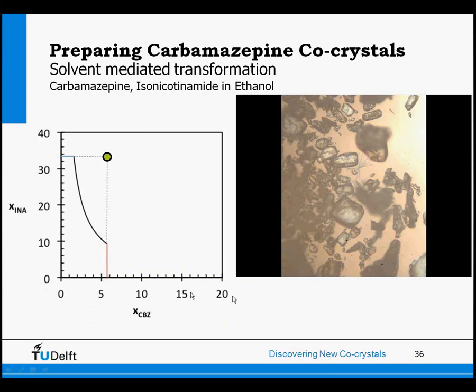Okay. So one thing you can do if you know the phase diagram is to prepare a composition in this point. So you add pure crystals of carbamazepine to a microscopic vial in such a way that you get this concentration in the end if you also add the solvent. You can also add Isonicotinamide crystals, and then you get this composition. And the moment you add ethanol, the crystals will start to dissolve and concentration increases, and you will enter the co-crystal region, and you get supersaturation towards the co-crystal, while you get undersaturated solution towards the pure components.